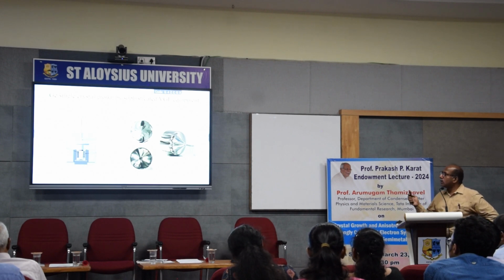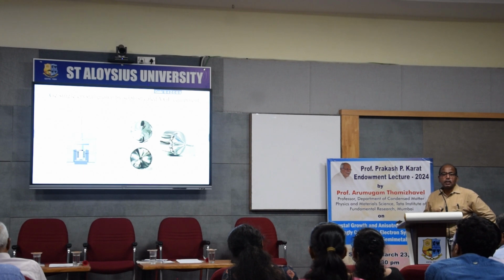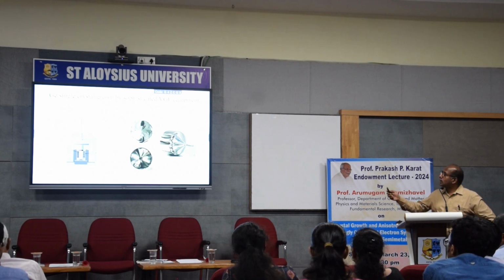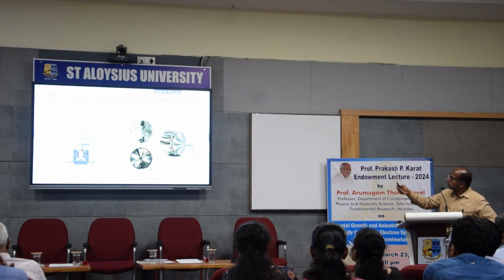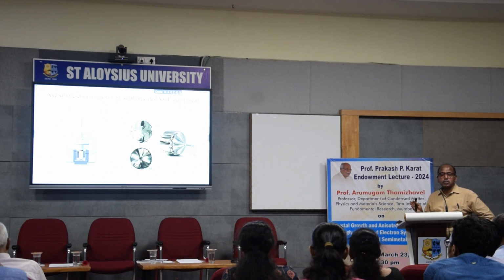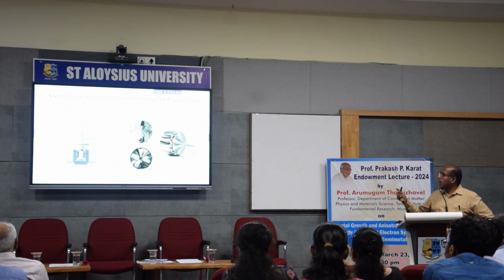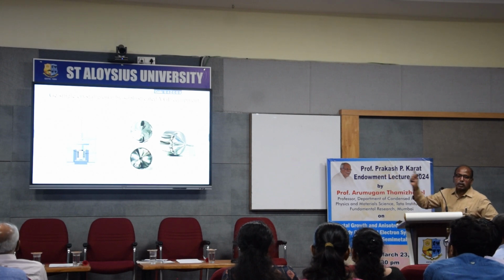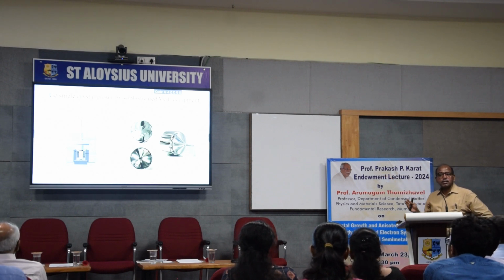High quality single crystals of germanium have been grown by this Bridgman method. Germanium melts at 938 degrees centigrade, and you can see that beautiful germanium single crystals have been grown. These germanium single crystals are used as radiation detectors, and these are very, very important. If you have 5 to 6 kilograms of germanium like this, it's worth a few lakhs of rupees, a few tens of lakhs of rupees.